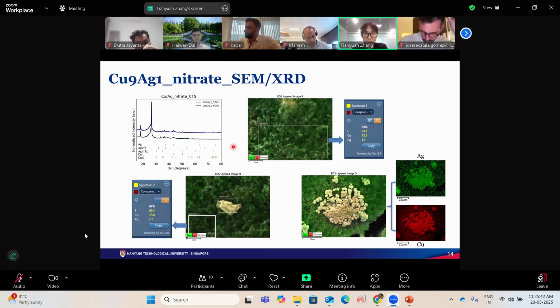And after this, we started to add a very small volume of silver nitrate salt to our copper nitrate salt, because appropriate silver may lead to the production of carbon monoxide, which can be further reduced to C2 products and improve the catalysis efficiency. And we did XRD, and we confirmed that there are copper and copper oxide in this sample, but the silver compound is very hard to identify because the volume is too small.